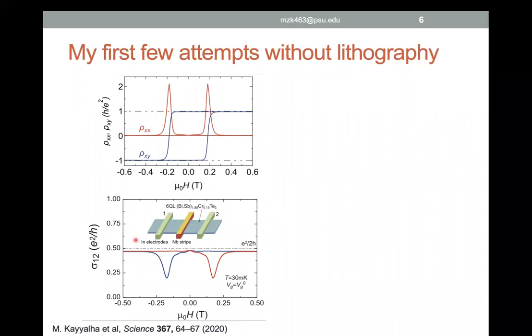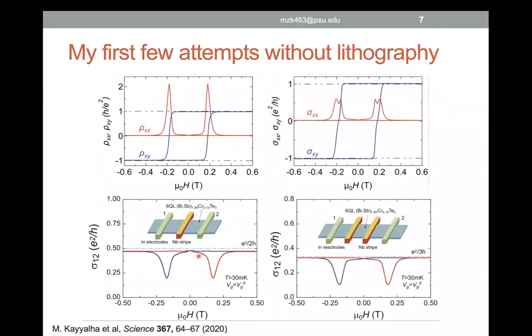And then I looked at the 2 terminal conductance measured between terminal 1 and 2 here. However, what I observed was that this 2 terminal conductance is always almost half quantized. So this was measured in a bunch of millimeter size samples. And then I also tested the theory that if you have more than one superconductor, if this half quantization is caused by the chiral Majorana mode, then it doesn't matter, you should still see half quantization.